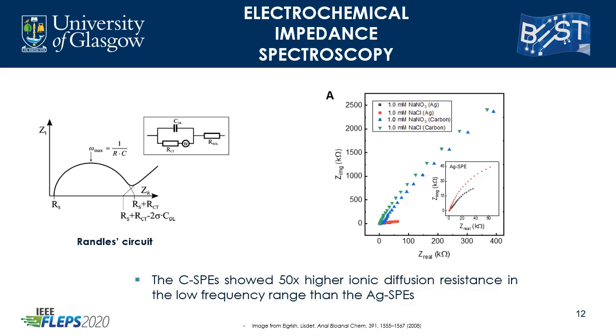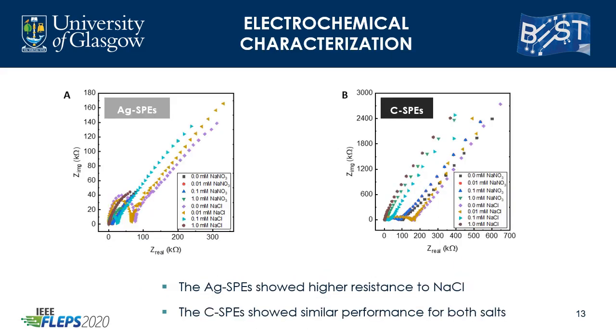When analyzing the Nyquist plot for the silver and carbon electrodes, the carbon electrodes showed high ionic diffusion resistance in the low frequency range. In fact, more than 50 times higher when compared to the silver electrodes. This could be due to the high resistance of the carbon electrode and the charge accumulation on the surface of the electrode due to the double layer formation. Meanwhile, the silver electrodes offer high conductivity and charge accumulation due to the enhanced non-faradaic reactions on the electrode.